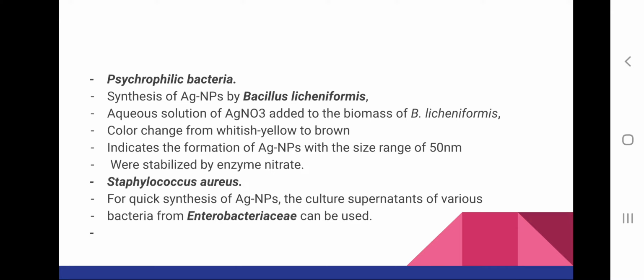Then Bacillus licheniformis is used for synthesizing silver nanoparticles, in which we are adding this Bacillus licheniformis biomass onto aqueous AgNO3 solution, and after addition of this bacteria, this solution changes from whitish yellow to brown color, and this change in color indicates the formation of silver nanoparticles, and usually nanoparticles of 50 nanometer size can be synthesized using this bacteria. Another example is use of Staphylococcus aureus, and it can be used for synthesis of nanoparticles. And for quick synthesis, enterobacteria can also be utilized.